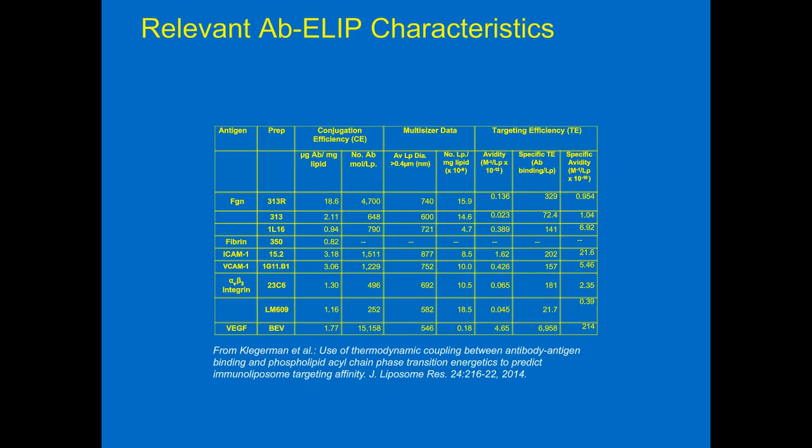But now what we're using is a method that involves a small Sepharose CL4B column, which has been preconditioned or preloaded with plain liposomes, with untargeted liposomes.